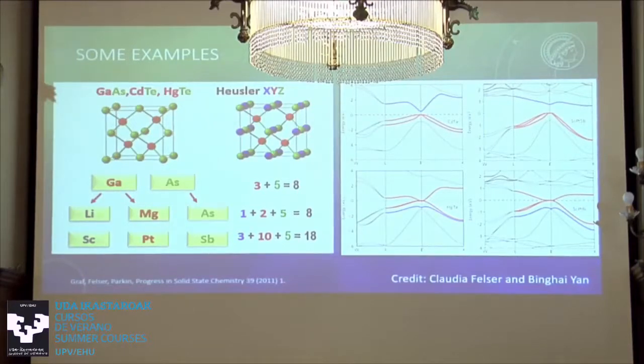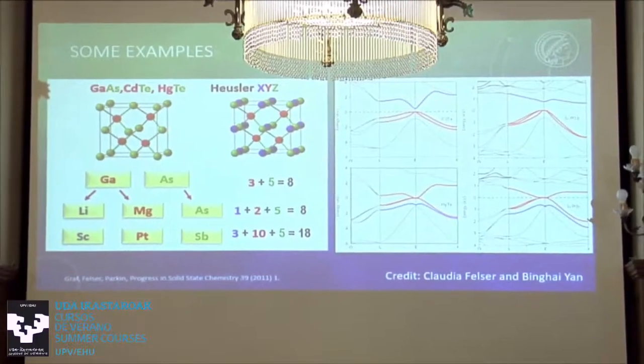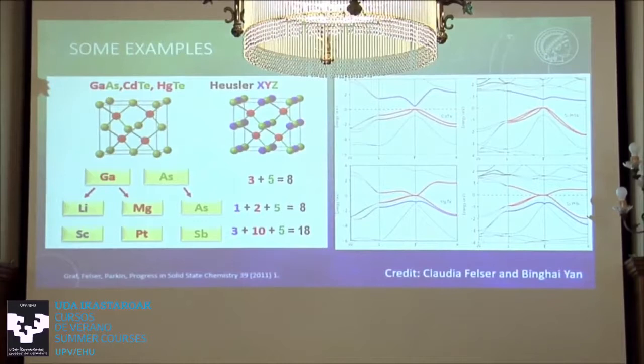You can see that here in this band structure plot. For example, cadmium telluride and mercury telluride both have 8 electrons per valence cell, and they're charge-balanced compounds. Here you have the gap, here the bands touch, but it's still a charge-balanced compound. There's a zero band gap here. And the same works for more complicated compounds like scandium, platinum, antimony, or scandium, platinum, bismuth, where you wouldn't intuitively think so. Okay.